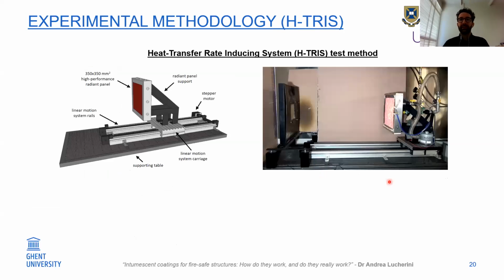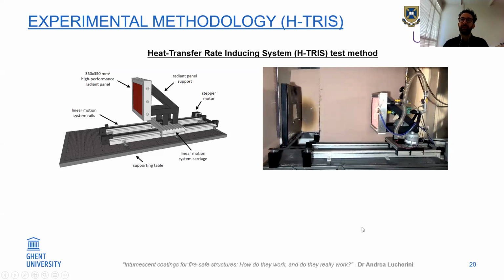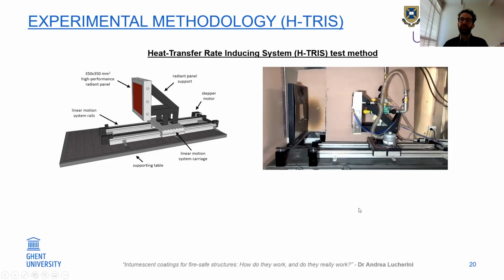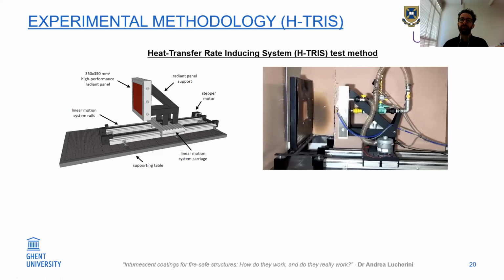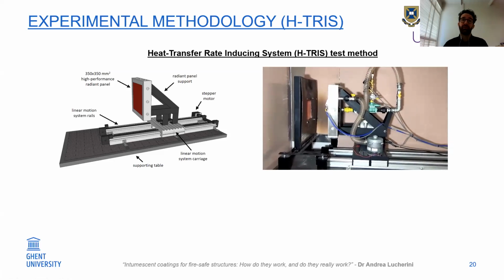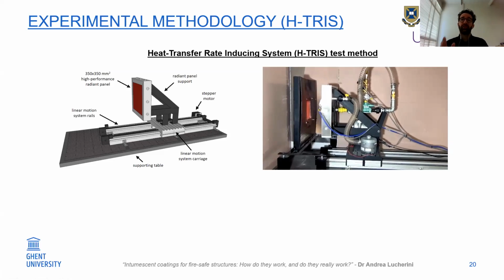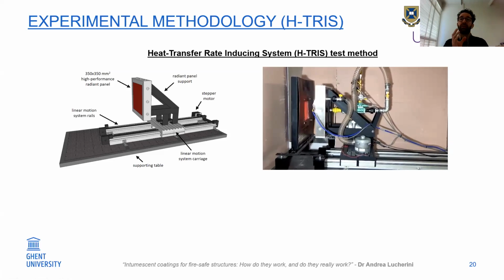So then the next point was to understand and define an experimental methodology in order to study how intumescent coating behaves when exposed to fire. This was done by selecting a fire testing methodology called HTRIS, Heat Transfer Rate Inducing System. The concept of this system is to place a radiant panel that achieves a very stable temperature and move the radiant panel on a computer-controlled linear motion system. By controlling the relative position of the radiant panel and the sample, you can control the heating conditions.